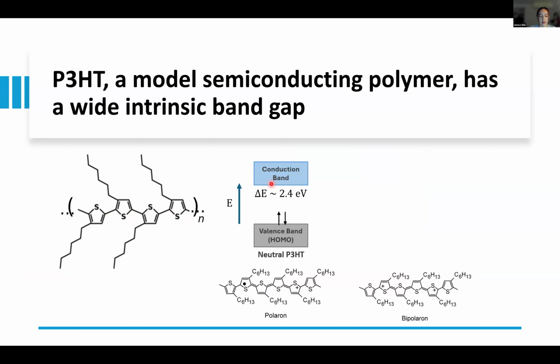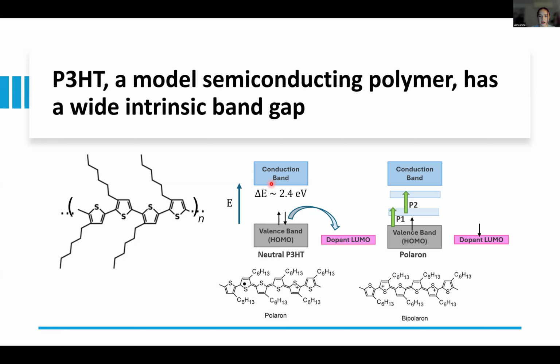And in the case of semiconducting polymers, we can introduce a molecule which has a lower energy LUMO than the HOMO of the polymer. And this is going to oxidize the polymer, resulting in the creation of charge carriers, which are evidenced by these new P1 and P2 transitions in the polaron case. When we remove one electron, this results in a polaron. And when we remove two electrons, this results in bipolarons, which actually decrease the conductivity because their mobility is poor.